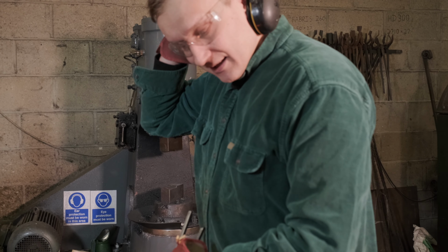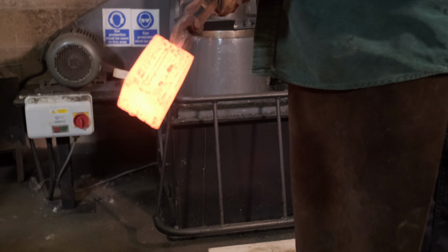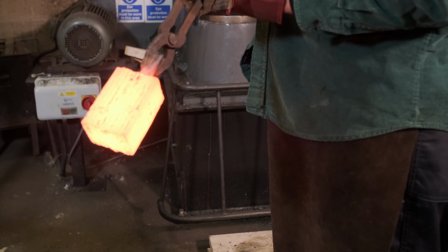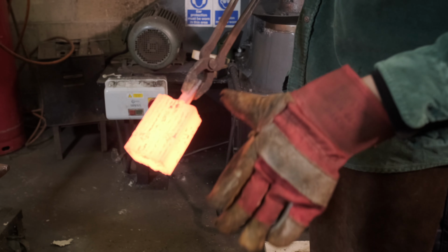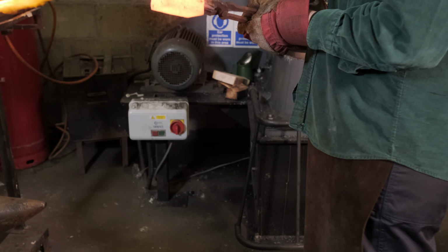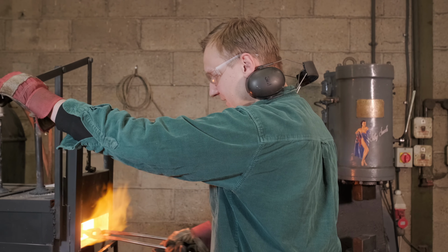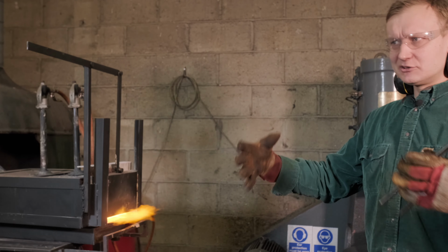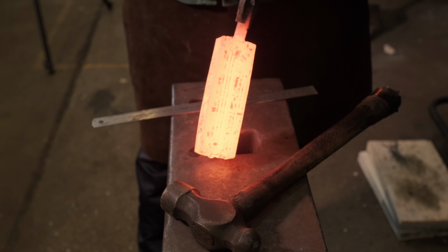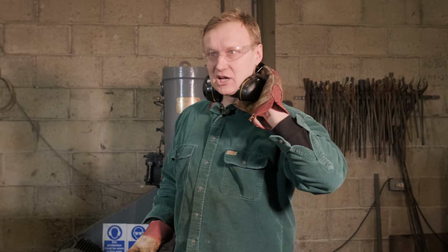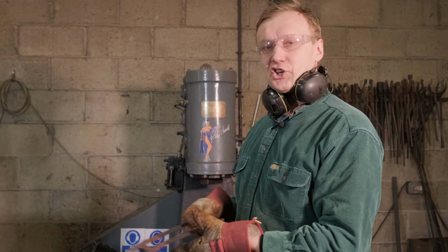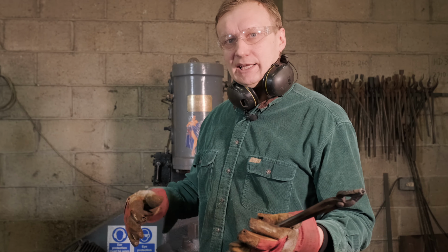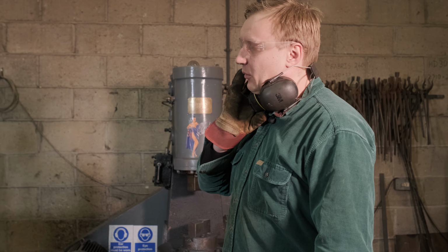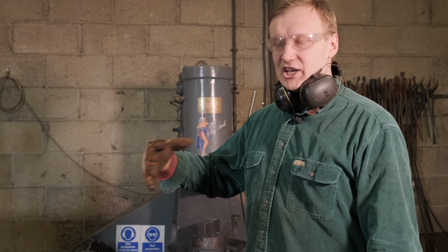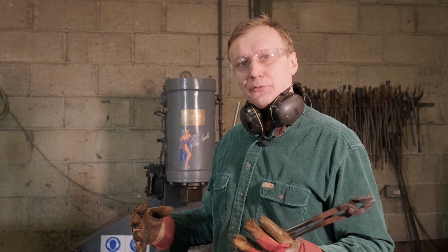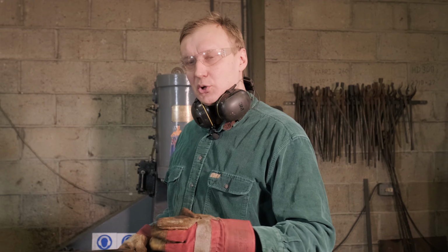It looks nice and welded, even though we had that initial split because my tack weld let go. Now it looks quite solid. It's gonna go back in the forge. Get it up to temperature. You don't want to let it cool down too much, because if there's any issues with the weld, it's gonna start splitting. And now that the steel has been hot for a certain amount of time, the scale is going to form much more quickly, and this is what you want to avoid.